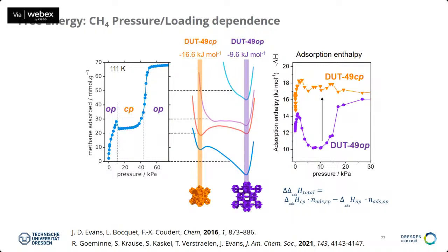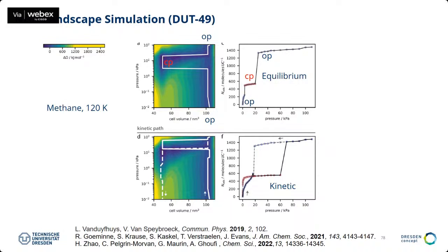And this leads to a situation where essentially the contracted pore phase becomes more stable for an intermediate pressure. And only at high pressure is there so much methane that the best situation is to have a large pore, to absorb a lot of gas, basically. And then the sponge is really opening up again, and then the large pore form is the stable one again. So with this, we can understand also all the energetics behind this transformation. And nowadays, theory is so advanced. I'm always impressed by all the theoretical developments, and it's so valuable to cooperate with theoreticians to get a better understanding of what is going on. And this was a cooperation with the group of Van Speybroeck and also Jack Evans, basically, in 2021.